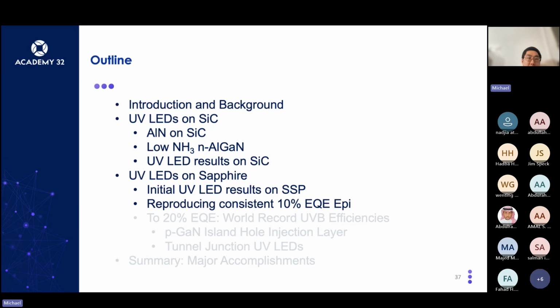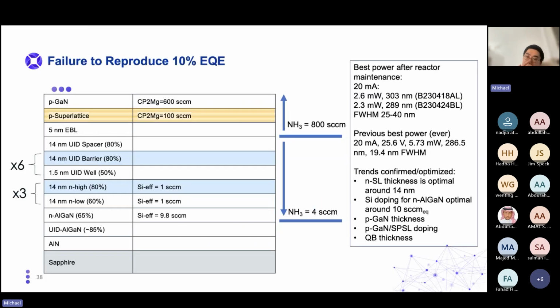So these results were great, but what happens is that when we tried to grow these LEDs after reactor maintenance and use of the reactor on different projects, we could not reproduce these results easily. And this took quite a significant amount of time to get back our conditions. Previously our power was around 4 to 5 milliwatts. This is quick test power, as I explained earlier with the indium contacts. So the best power ever was 5.7 milliwatts at the time, and we could only reproduce 2.3 to 2.6 milliwatts. So of course, this was through a lot of tuning of all of the layers in the LED.